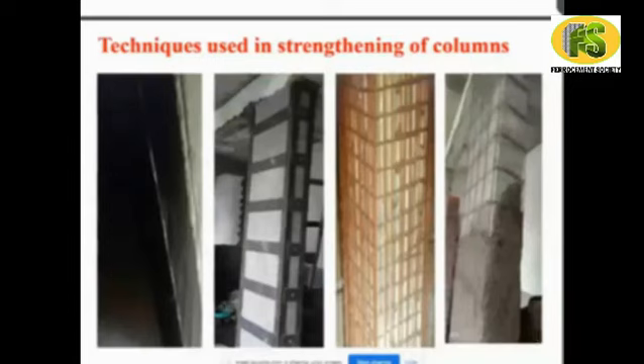That is normal, because normally about 40 thickness, any way you go, we get 25 to 35 or 40 thickness of ferrocement, because the thickness of bars plus cover plus mortar and meshes goes to 35, 32 or 40 like that. So this is the regular nominal reinforcement you have provided. This is normal.